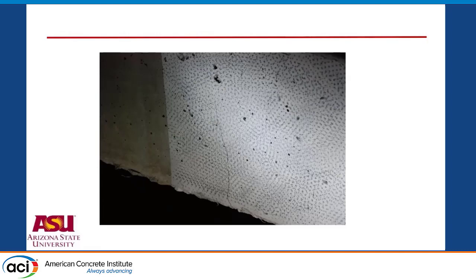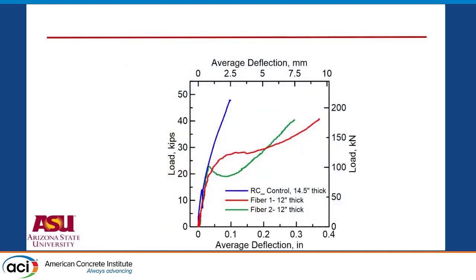And then what we can do is compare this result to the standard design, which is the reinforced concrete, shown in blue, versus the 2 fiber systems, fiber 1 and fiber 2. And note that here the thickness has changed. The thickness is about 15% lower. And when I talk about the cost, the fact that you can reduce the thickness by putting in the fibers was good enough for them to fund the project. They figured that it's going to save them $500,000 per mile by simply reducing it by 2 inches.